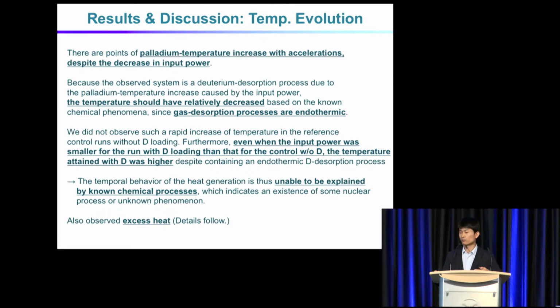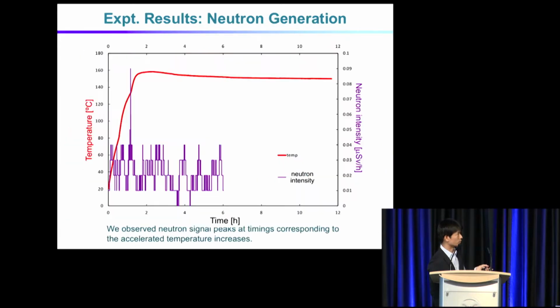We didn't observe such a rapid increase or acceleration of temperature in the reference control runs without deuterium loading. And even when the input power was smaller for the main runs with deuterium loading than for the control runs without deuterium, the temperature attained with deuterium was even higher, despite the containing endothermic deuterium desorption processes. So the temporal behavior of the heat generation cannot be simply explained by non-nuclear or physical chemistry processes, which indicates the existence of some nuclear processes or unknown phenomena. And we also observed excess heat, as I will show later.